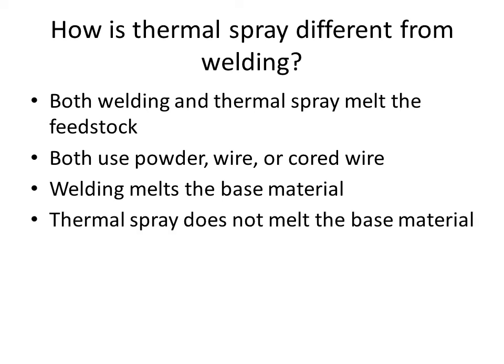How is thermal spray different from welding? Both welding and thermal spray melt the feedstock — that's where they're very similar — and both use a powder, a wire, or a cored wire. That's why they're often confused. But the big difference is: when you weld, you melt the base material. In thermal spray, you don't melt the base material. It's again just a mechanical bond.